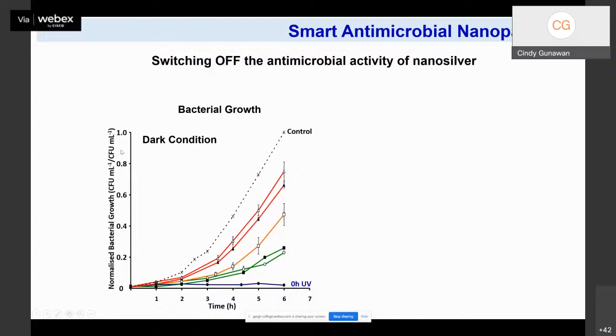So this is the growth profile of the E. coli bacteria as a function of time. The blue profile here is the growth profile when the model bacterium is exposed to the nanoparticles without any illumination, so as prepared. If you remember, you will have a silver 1 deposit here. As you can see, the growth of the bacteria is completely inhibited. But when you expose the bacteria to nanoparticles that have been exposed to increasing time of UVA illumination, you can see more and more growth, meaning less and less growth inhibition, which means that the antimicrobial activity has been switched off.